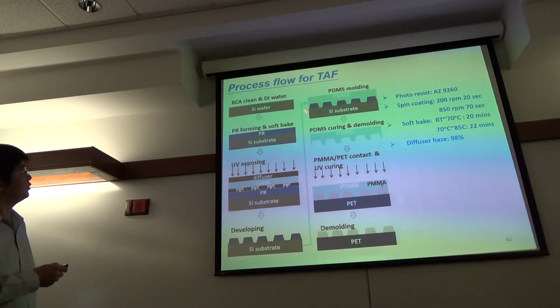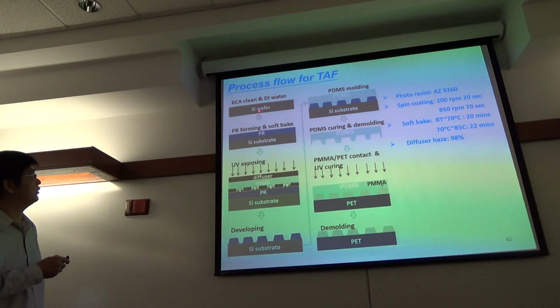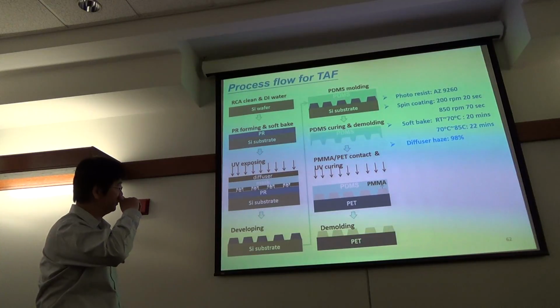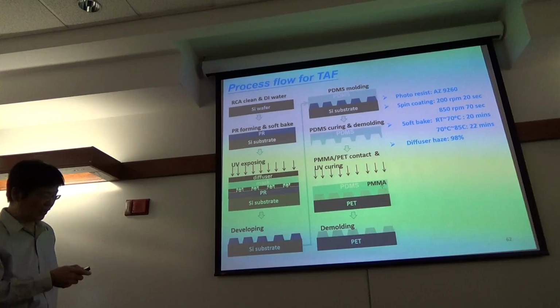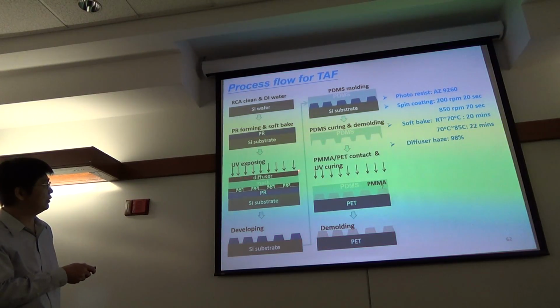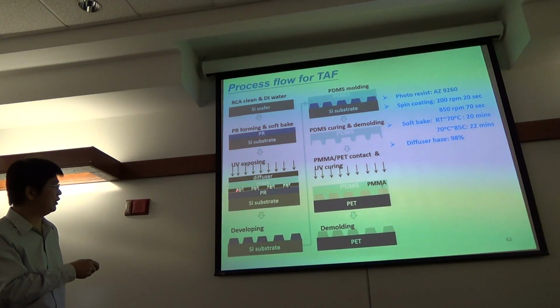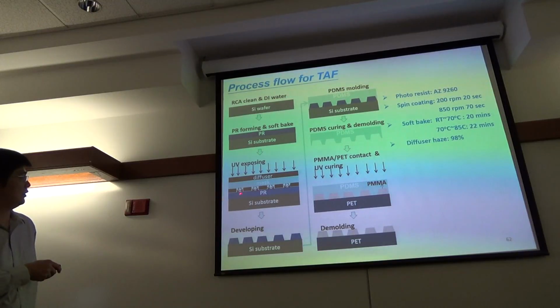So that's the fabrication flow for the trapezoid. First, we use a silicon wafer and a photoresist, and that is called diffuser lithography or something like that. Anyway, we use a mask, and upon the mask, we put a diffuser. So during the UV light irradiation, there's a slope over here onto your photoresist.